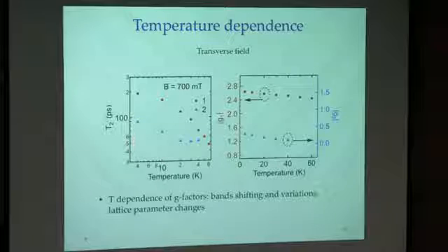Further, we also have the temperature dependence of the spin dynamics in a transverse magnetic field. The spin dephasing time also decreases with temperature. And also for the G factors, we see a pretty big change when increasing the temperature from 4 Kelvin up to 60 Kelvin. For example, the electron G factor decreased by 0.2. And the hole G factor changes from 0.3 to really small. It cannot be identified above 40 Kelvin.